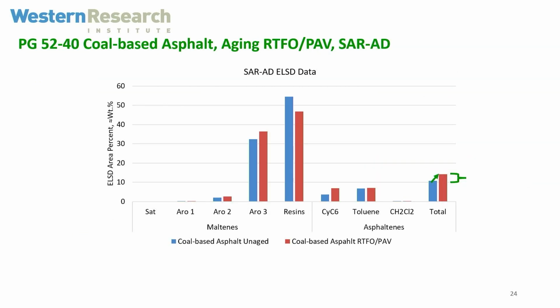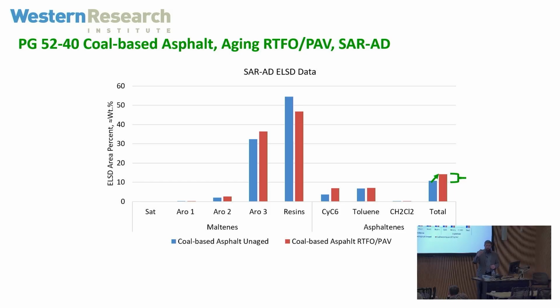This is one of the big problems that we encountered, which is a huge hurdle that took us some time to overcome, is the oxidation behavior. Because asphalt sits on the pavement, and over time it becomes brittle because it's just oxidizing in the environment. And it just stiffens. It loses its ability to relax stresses. So you have thermal stresses when your material heats up and it cools down. And then also you have traffic load, which is constantly stressing it. If you can't relieve those stresses, you're going to crack. And so we want material that's not going to age any worse, hopefully age better than a petroleum asphalt.